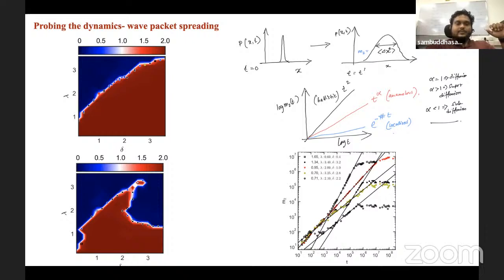So if we plot a dynamical phase diagram, but the color code is the power alpha, we see that there is a transition, and the transition points are marked by this blue dot and black dot. They show truly super diffusive and sub-diffusive behavior, as I have shown in that other plot at the bottom. And we have extrapolated this thermodynamic limit behavior, and this is indeed a super diffusive or sub-diffusive behavior in the cases where we mark it.